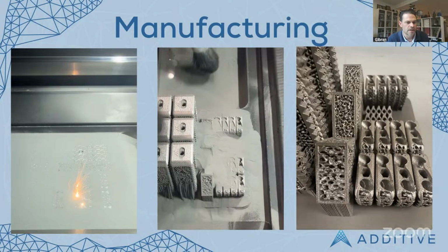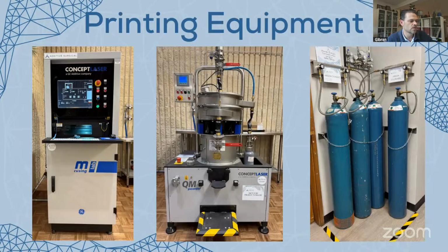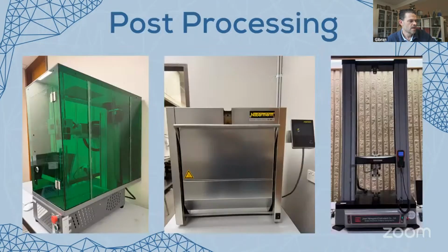So what happens after this is, this is the printer, the sieving station, the argon gas. Then these are some of the post-processing pieces of equipment. There's a laser marker to laser mark the implants. There's a heat treatment machine, and that heat treatment anneals, or lets the metal reduce all its internal stresses, because after it comes off the titanium printer, there are some internal stresses that you need to heat treat to basically relax the metal and make it even softer.